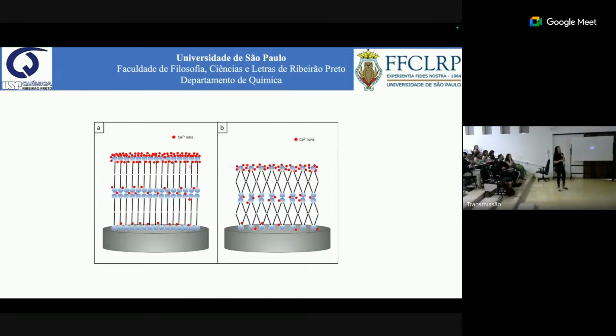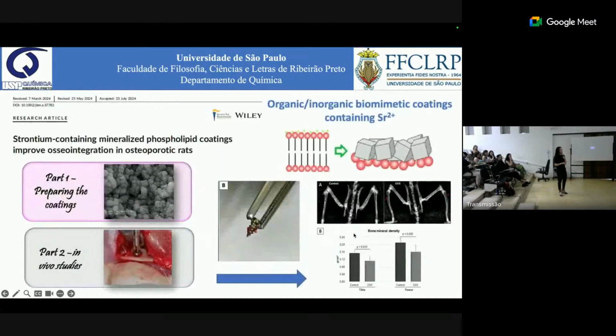We can play with lipids with different structures, like lipids with only one carbon tail, lipids with double carbon tails. We can play with a surface with higher affinity for calcium, with lower affinity for calcium. We can play with the number of layers that we are depositing on titanium. And as a first example of this kind of films and coatings, I will show the result of a